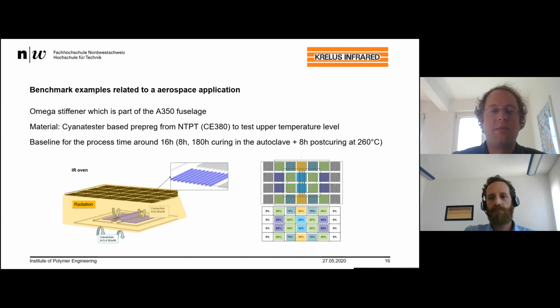And most of the common manufacturers have the problem that they only have an autoclave which is suitable to go up to 180 degrees. So therefore, the baseline of this process for this material is nearly 16 hours. So you need 8 hours to cure the material at 180 degrees in the autoclave, and then most of the time people apply an additional post-curing in a convection oven at 260 degrees. And so we have taken this example to show the potential of the technology.